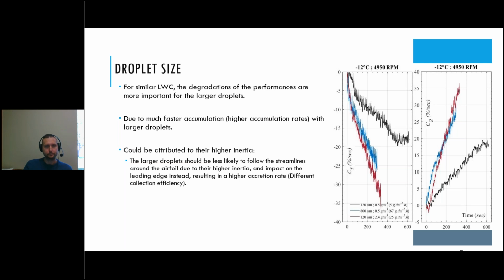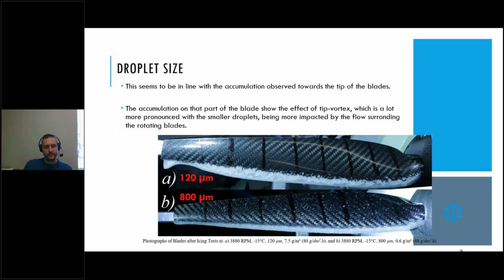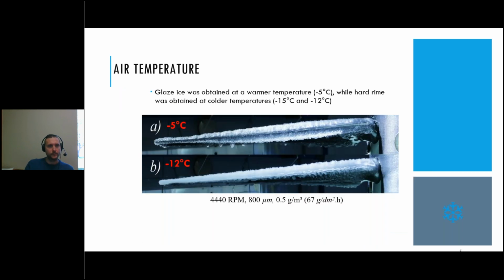Next slide, please. And this seems to be in line with the accumulations observed towards the tip of the blade. So you see 2 examples of ice accumulations with the 2 different droplet sizes. And we see at the tip of the blade the effect of the tip vortex, which is a lot more pronounced with the smaller droplets, being more impacted by the flow surrounding the rotating blades than the larger droplets. Next slide, please. Then we'll look at the effect of the air temperature.